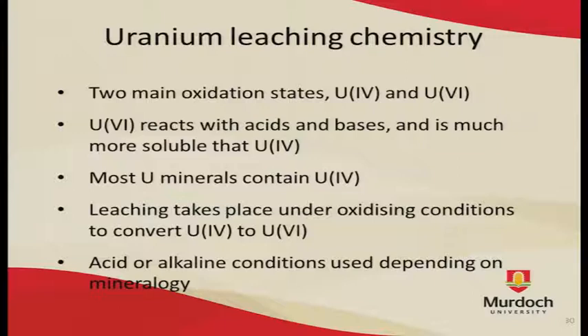Now, most uranium-bearing minerals contain uranium-4, so it's necessary to oxidize it over the course of leaching. It's necessary to oxidize it first to get it into solution, which is why most uranium leaching processes take place under oxidizing conditions. There are a few minerals out there that contain uranium as uranium-6. These are mostly ones that form weathered deposits, so it's been naturally oxidized already. It can be leached under acidic or alkaline conditions. The choice between the two depends largely on the mineralogy of the gangue. If there's too much acid-consuming gangue, then acid leaching will become uneconomical.